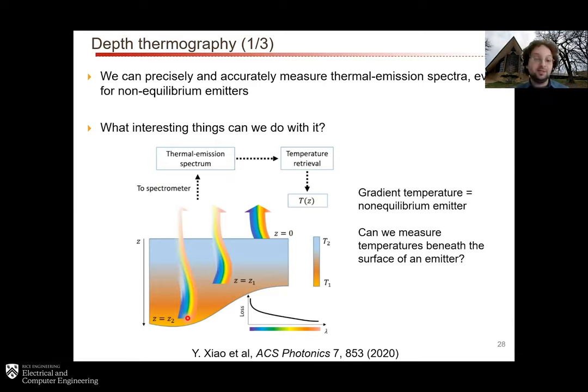And so the way to understand this is actually quite straightforward, and you can see it in this diagram over here. Essentially, anything that's thermally emitted from the top surface is not going to be attenuated anymore. It's just going to be propagating through free space, and eventually it hits your spectrometer. Anything that is emitted from depth, if you have a material that has some amount of optical loss, it's kind of a semi-transparent material, some of that thermal emission is going to be attenuated before it makes it into your spectrometer. However, that attenuation is going to have a wavelength dependence, because any lossy material has some sort of dispersion associated with it and some sort of loss as a function of wavelength. And therefore, by looking at the spectrum, you should be able to figure out what the temperature is at different points along the depth. So I think we have the first question, so I'm going to quickly look at that.